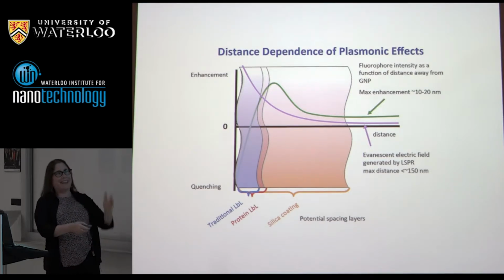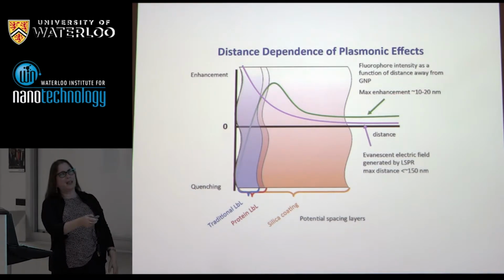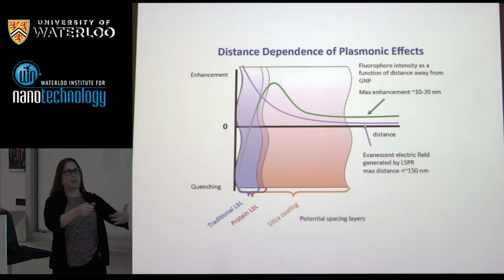So what do people find in the literature from lots of different systems? They find something like this. Somewhere between 10 and 20 nanometers out, you're going to get an apparent maximum. So really this green curve here is the superposition of quenching when you're too close and enhancement when you're some distance away, and then the apparent maximum is somewhere here, 10 to 20 nanometers.